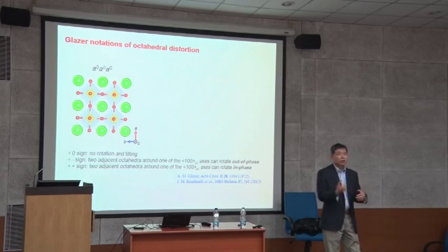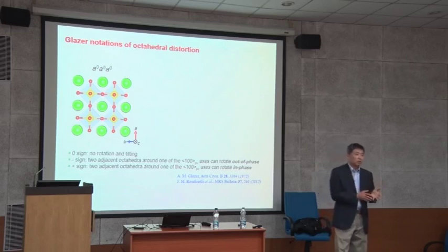Okay? We also use a different technique. We grow the films at roughly 10 to the minus 3 or 10 to the minus 2, quite high oxygen partial pressure, at low temperature, like 550 degrees Celsius. So we have two different recipes. When you grow at low temperature with a lot of oxygen, you don't have to do extensive post-annealing, like when growing at 10 to the minus 6 torr at high temperature. And the end result is very similar.